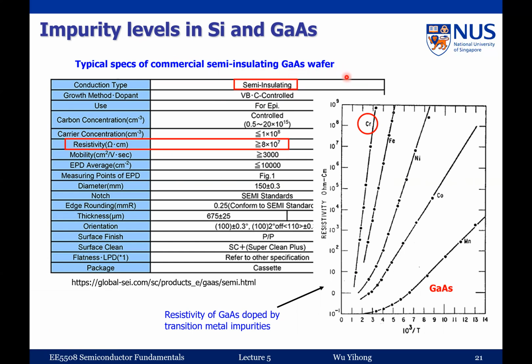If some of you may have used this one before, you can see that it's semi-insulating, right? And then you look at this resistivity, you can see it's very high, okay? And if you look at what can make this gallium arsenide semi-insulating, look at this temperature and this resistivity, and this is the dopant, right? You can see chromium, iron, nickel, right? Especially chromium. If you dope gallium arsenide with chromium, you have very high resistivity, right? Room temperature is somewhere here, right? Because this is 1,000 divided by temperature in Kelvin. So this is room temperature basically here, right? You look at room temperature, and the resistivity of this chromium doped gallium arsenide is very, very high. So basically, it's semi-insulating, right?